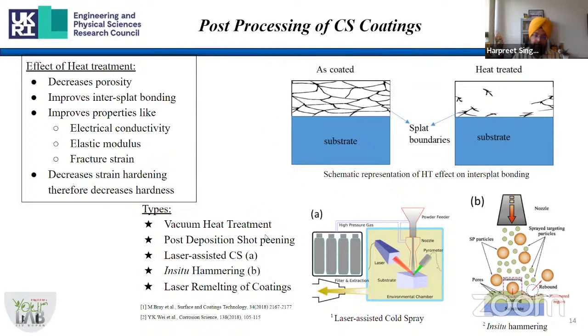And there is a lot of development in this domain in terms of creating technologies for post-processing of cold spray coatings. For example, vacuum heat treatment is traditional, but then we have post-deposition shot peening, as we do in other components as well. Laser-assisted CS is another hybrid technology, which has been utilized for in situ help to mitigate the effect of this brittleness. And in situ hammering is another concept where we have these solid, hard particles, which simultaneously do this hammering. In one sense, we are doing this peening effect as well as coating simultaneously. And of course, we can use laser remelting of coatings as well. But each of these processes will have its own advantages and disadvantages, and we have to select accordingly wherever we wish to go about it.